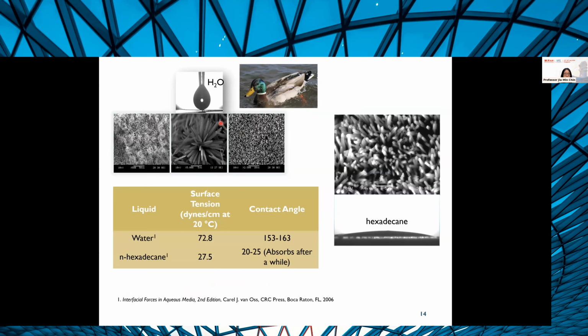And what we ended up seeing was that when we tried to measure the contact angles of these materials to water, we ended up with such a superhydrophobic material that we really struggled to deposit even a drop of water onto the surface to measure the contact angle. If you measure contact angle, you usually have a pipette, and then you deposit this drop of water. But when we lifted the pipette tip up, that drop of water preferred to stay with the pipette tip, and it just lifted up with it as well. So that was a little bit challenging. And our material really reminded us of how water just bounces off a duck's back.